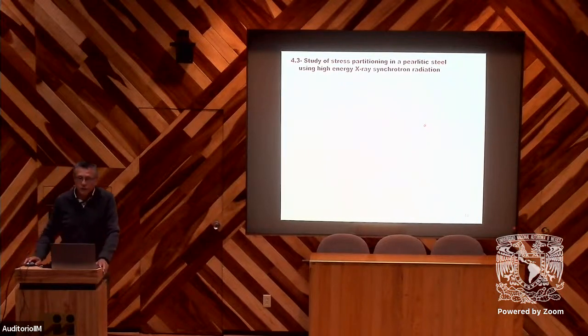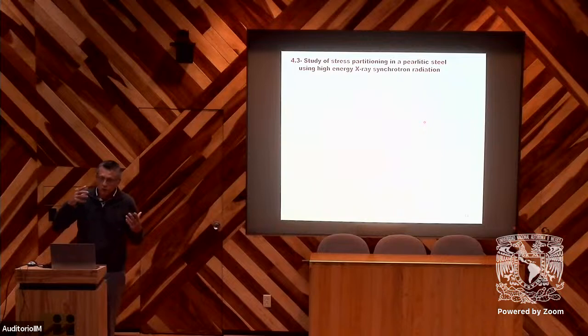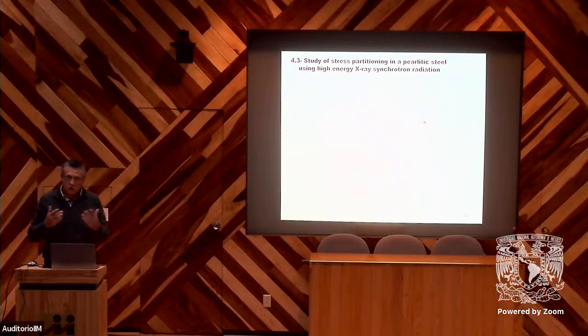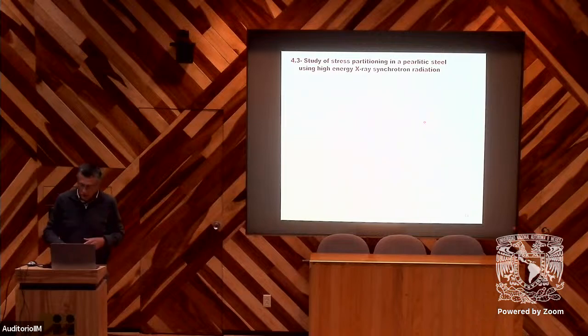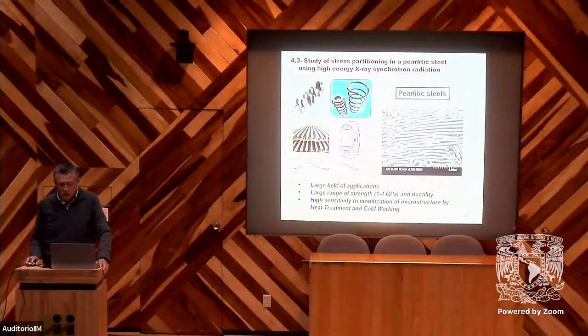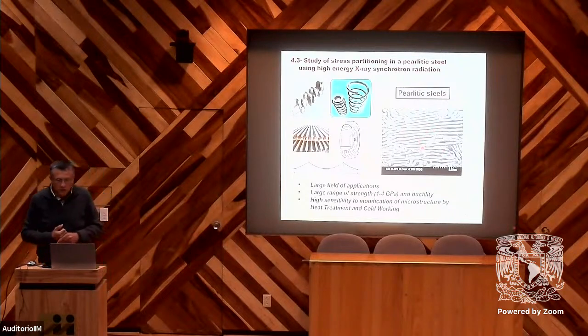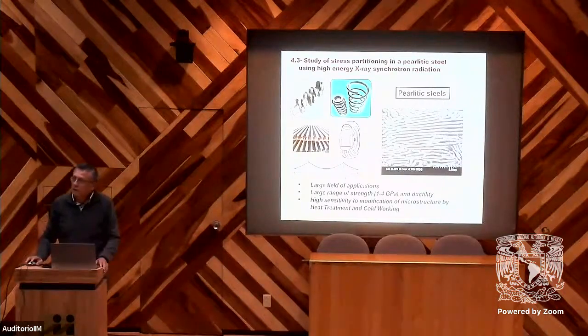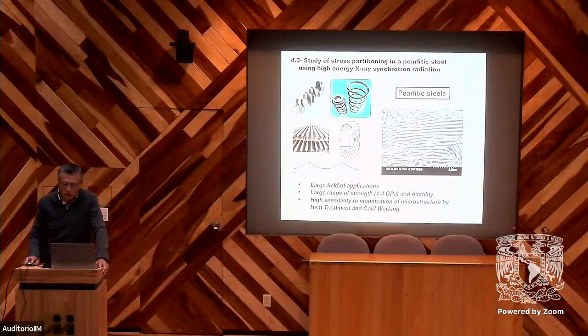And now, the third study uses X-ray synchrotron radiation to study the stress repartition between the ferrite and the cementite in pearlitic steel. Pearlitic steels can present very fine structure, and this material presents a very large field of application and a very large range of strength, because the structure and the behavior are very sensitive to cold working and heat treatment.